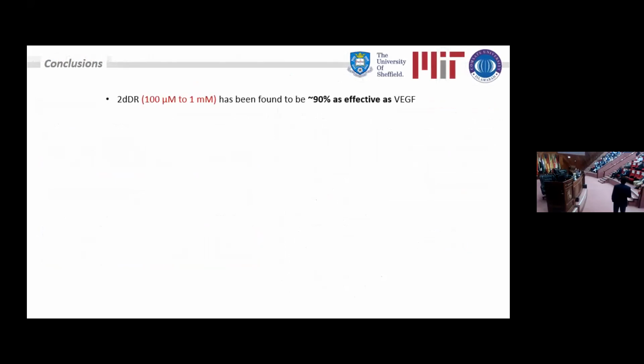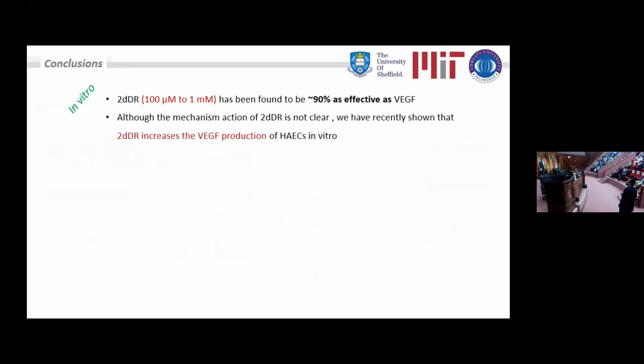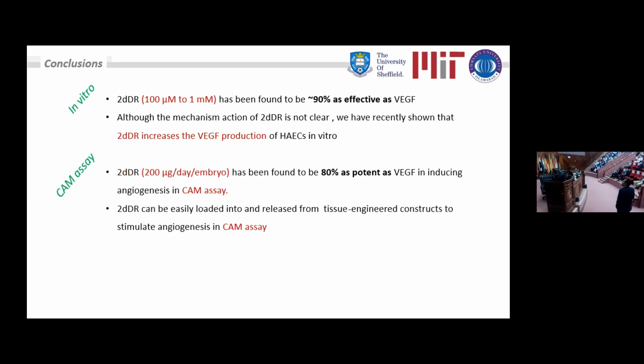So in conclusion, what we have learned from this is that 2-deoxy-D-ribose at 100 micromolar to 1 millimolar has been found to be 90% as effective as VEGF. Very interesting. Although the mechanism of action of 2-deoxy-D-ribose is not very clear, we have recently shown that 2-deoxy-D-ribose increases the production of VEGF, which is responsible for blood vessel formation. So what the CAM assay has shown us is that 2-deoxy-D-ribose at 200 microgram per day per embryo has been found to be 80% as effective as VEGF in inducing angiogenesis in the CAM assay.